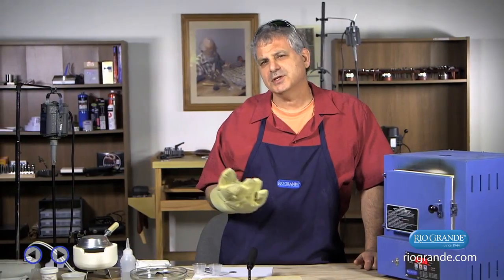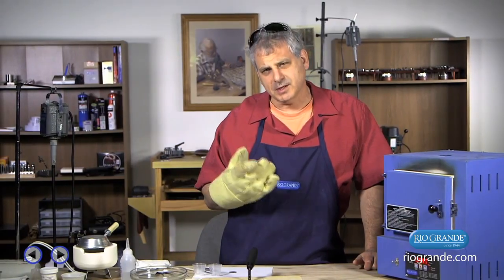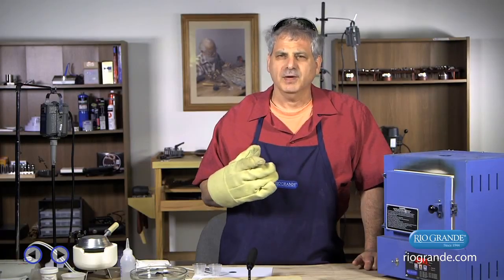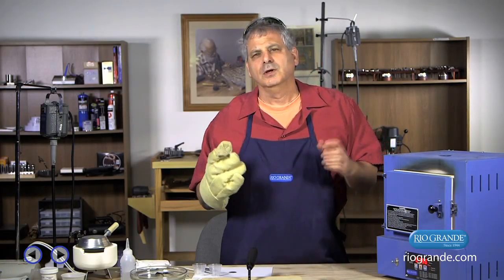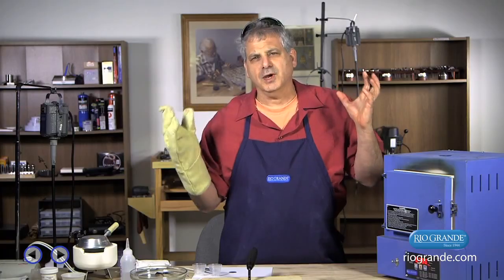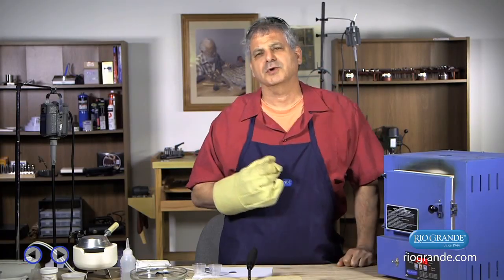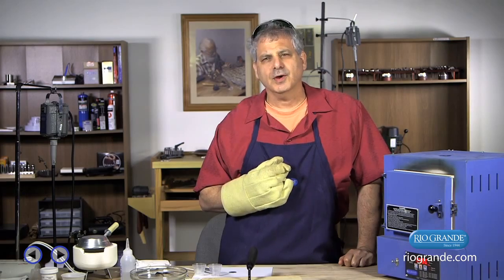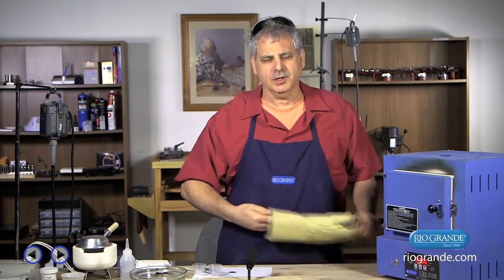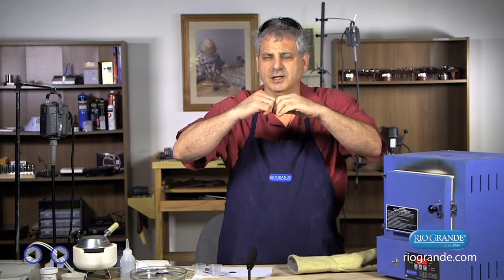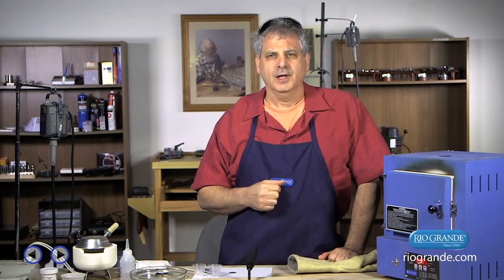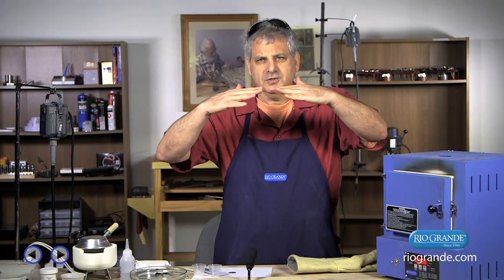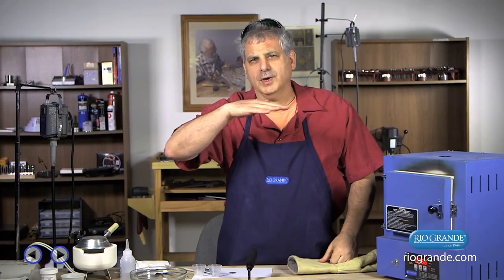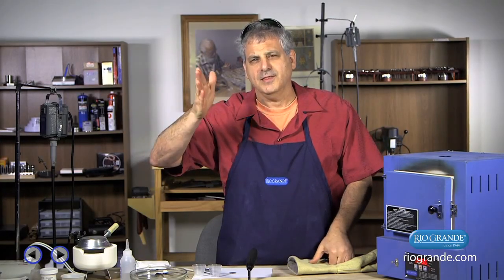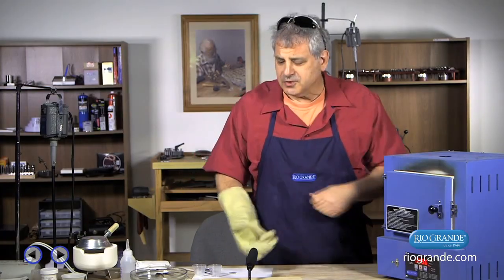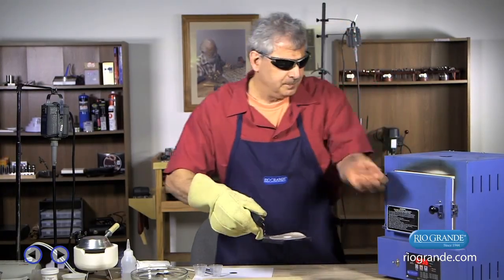So when the piece reaches a certain temperature for a certain amount of time, the enamel will start to melt. And it's going to start to pull upon itself, so each grain will pull into itself and form a ball of glass, and we're going to call that sugar. Then the grains are going to start to melt and join each other and get slightly glossy, and that's going to be called orange peel. As they melt and get closer and closer to being smooth, that's a whole range of orange peel, and then it's going to become glossy. So for this first firing, we're going to fire this to glossy.